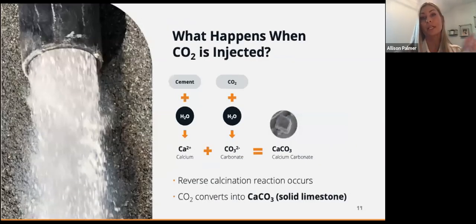This is a great representation of how the CO2 molecules look when injected into the mix. It almost looks like a dry ice or a snow. Naturally, a lot of people ask, is that going to have an impact on the temperature of the concrete? And the answer is no, simply because we aren't adding enough to make a difference. We're introducing about 1 pound of CO2 into every cubic yard of concrete, which is like 4,000 pounds of material. That 1 pound of CO2 just isn't going to have an impact on temperature. It'd be like throwing a handful of ice cubes into the back of a freight truck and expecting it to cool off. It's just not going to happen.